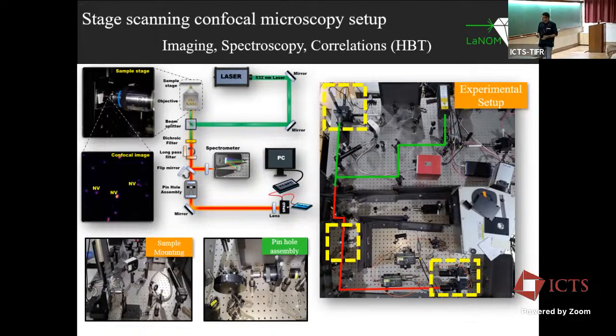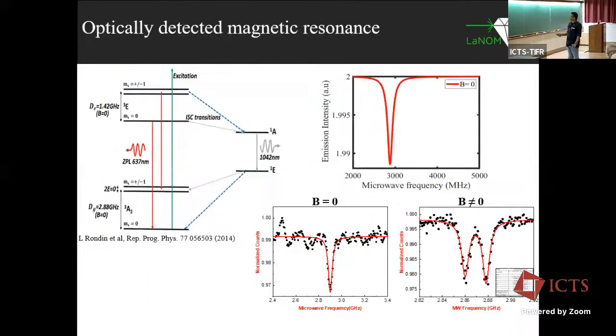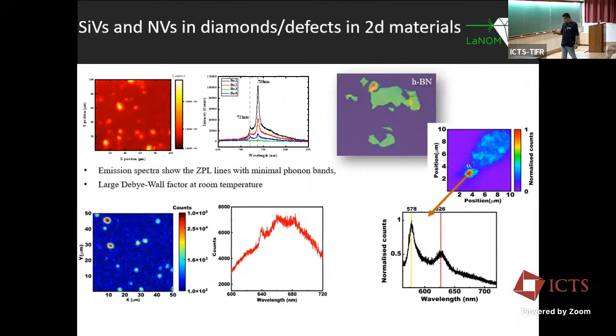But what we did, maybe just, we submitted the revised one. I'll show you one thing we did. Here we have hexagonal boron nitride. We took the sample and created defects using electron beam irradiation. One can also use electron beam irradiation here and create defects here also, so you can get site-specific defects. And there is a report in the literature on hBN where people used femtosecond lasers, scanned, and created line defects. So you get one emitter here, another here, another here. So it is possible.